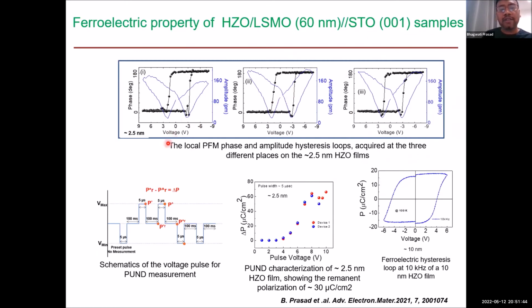And then we have done some more ferroelectric measurements. This is with the 2.5 nanometer films, which shows quite robust switching. We also did some PUND measurements to check the ferroelectric polarization, which comes around 30 microcoulomb per centimeter squared with the 2.5 nanometer films. This is when you do the testing with the Radiant ferroelectric testers, done at 10 kilohertz with the 10 nanometer films, and that also shows a decent ferroelectric loop, with the polarization somewhere around 15 to 20 microcoulomb per centimeter squared.